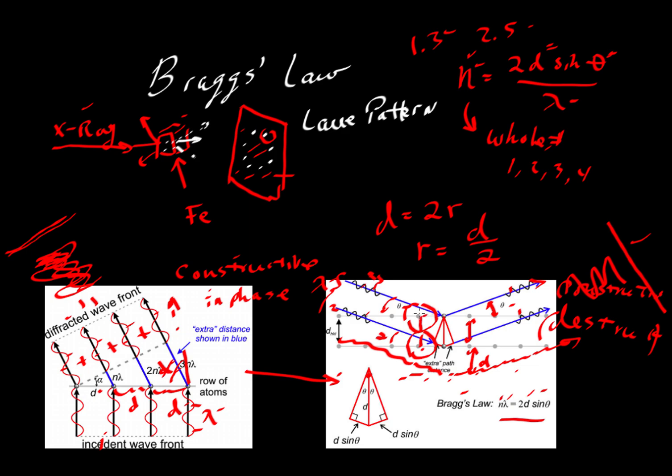If you play these kinds of games, the mathematics isn't quite that simple, but it's close to that being that simple. You can analyze stuff across the periodic chart and start determining the r values that we see in various materials. And then once you have all the pure materials set, you could start combining iron with oxygen and magnesium with oxygen and try to figure out how big the oxygen is. The radius of iron won't be the same if it's in the neutral state versus the 2 plus state. But you could play some games analyzing different kinds of materials and start to figure out not only that atoms exist, but how big they are, and you could start determining atomic radii.